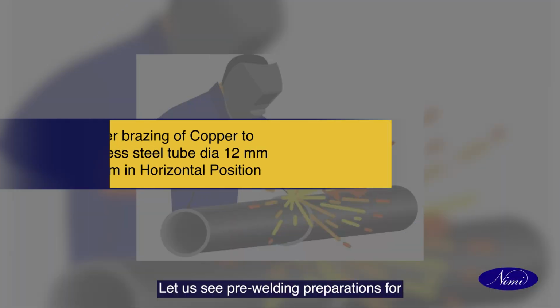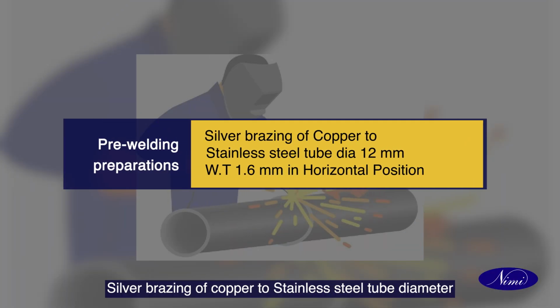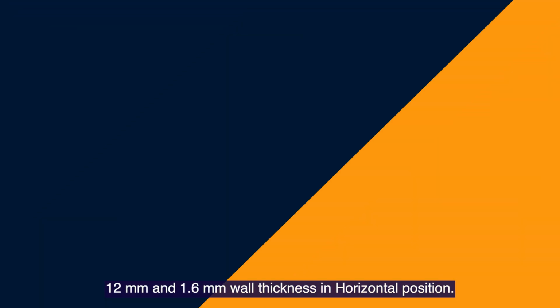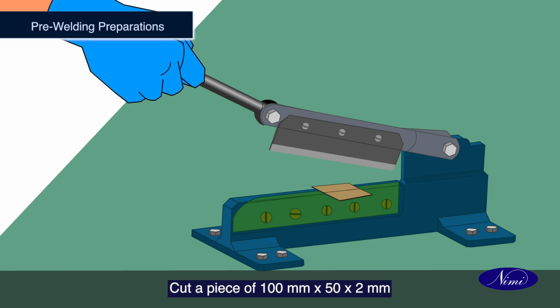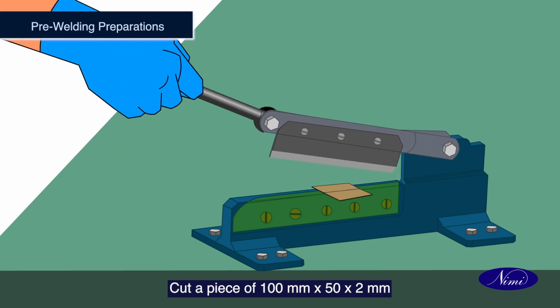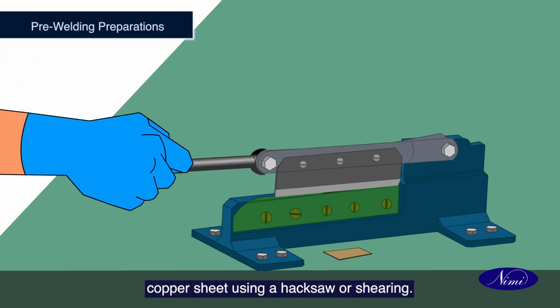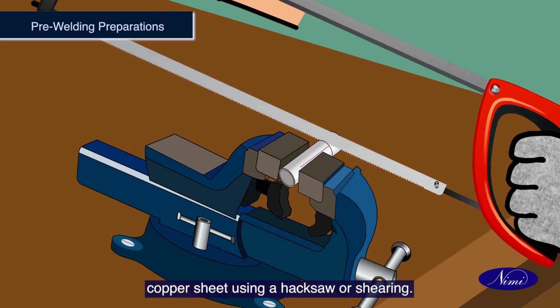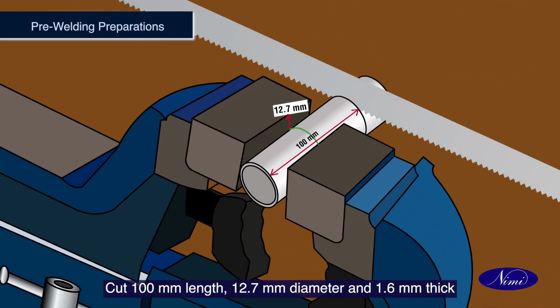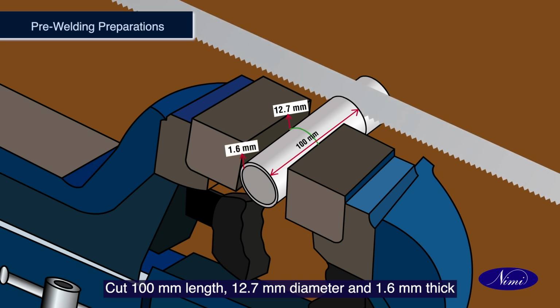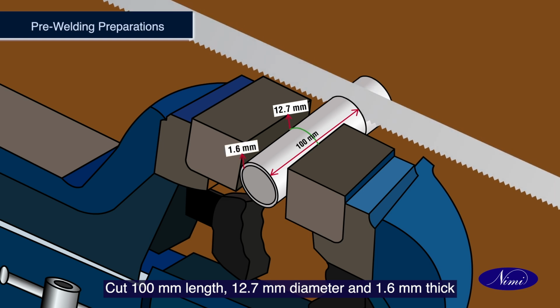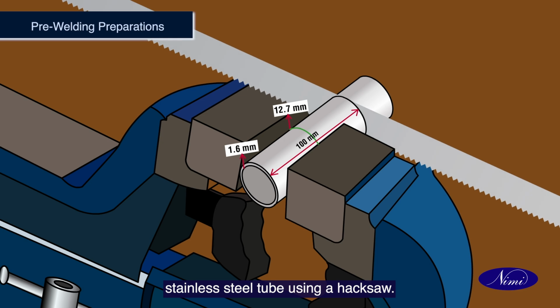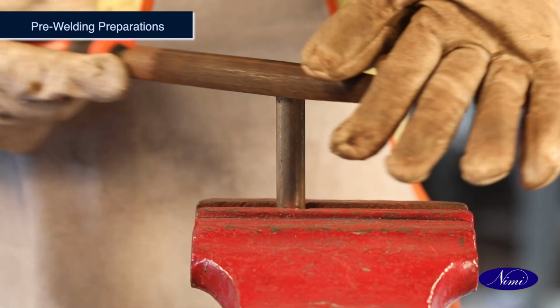Let us see the pre-welding preparations for silver brazing of copper to stainless steel tube diameter 12 mm and 1.6 mm wall thickness in horizontal position. Cut a piece of 100 mm by 50 mm by 2 mm copper sheet using a hacksaw or shearing. Cut 100 mm length, 12.7 mm diameter and 1.6 mm thick stainless steel tube using a hacksaw.